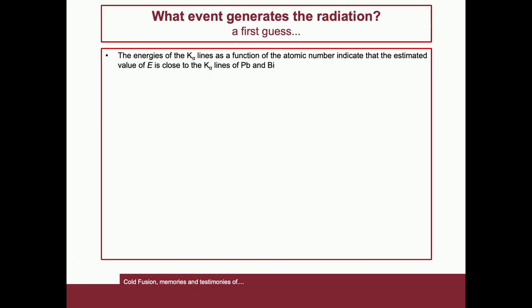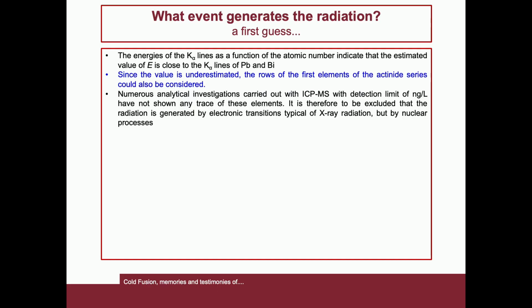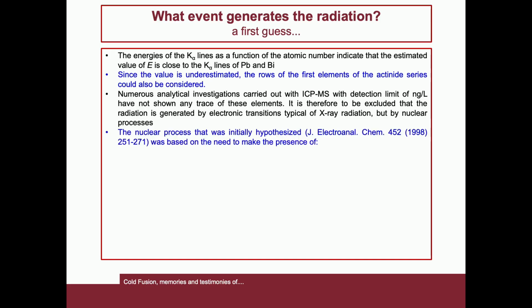What event generated the radiation? As a first hypothesis, the energies of the K-alpha lines as a function of the atomic number indicated that the estimated energy value is closer to the K-alpha lines of lead and bismuth. Since the value is underestimated, the K-alpha levels of the first elements of the actinide series could also be considered. Numerous analytical investigations carried out with inductively coupled plasma mass spectrometry, with a detection limit of the order of nanograms per liter, have not shown any trace of these elements, and therefore exclude that the radiation is generated by electronic transitions typical of X-ray radiation, but by nuclear processes.